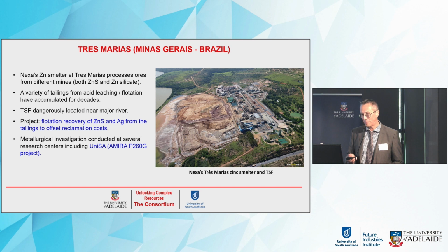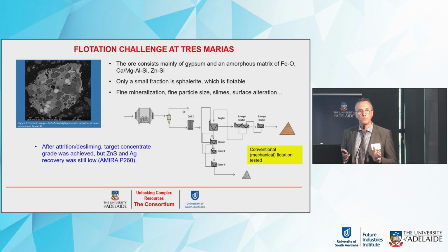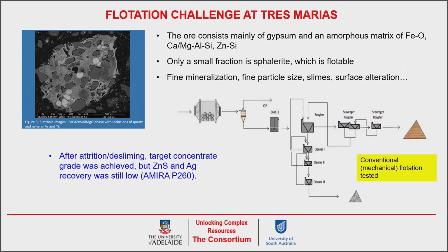And I decided to include this in my presentation today because this is the perfect example of a metallurgist's nightmare. Material from that tailings dam didn't look anything like a real ore. Basically it consisted of agglomerates of very fine particles of sphalerite and other minerals in a kind of amorphous matrix of gypsum and calcium, magnesium, aluminum silicate, zinc silicate stuff. Kind of something that you don't know how to deal with. Because ideally the only floatable species is sphalerite, which is the zinc sulfide, and the silver sulfide, silver in the sphalerite. And those were just very finely disseminated in this sort of amorphous matrix, which was almost impossible to recover.